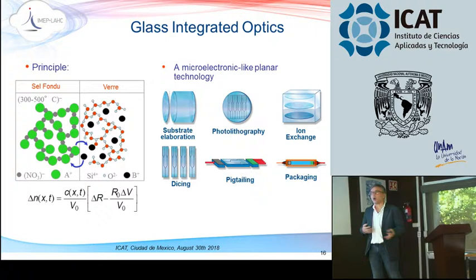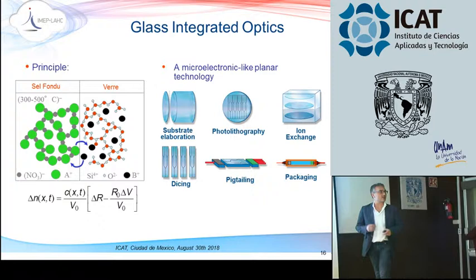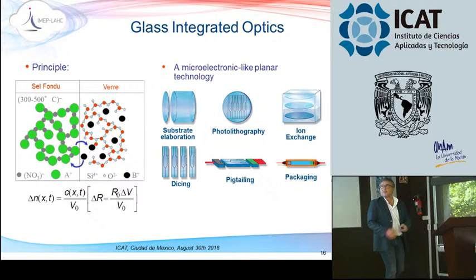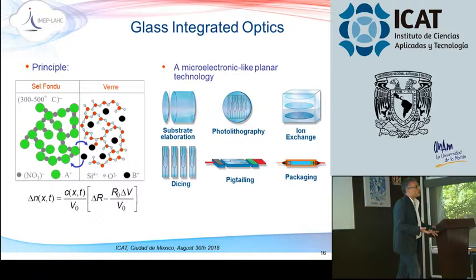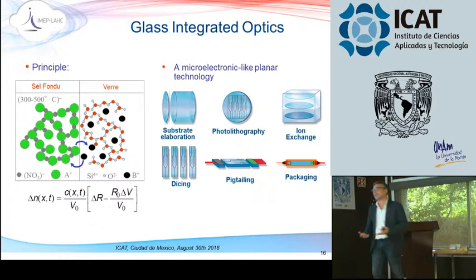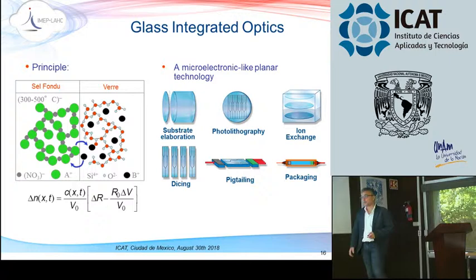These alkali ions are weakly bonded to the matrix. So if you heat the glass, they can move freely in the matrix. So if they can move, you can replace them by other ions, for example, silver ions. And doing so, you change the glass composition. If you change the glass composition, you change its refractive index. The variation of the refractive index you create depends on the concentration of the element you put in.